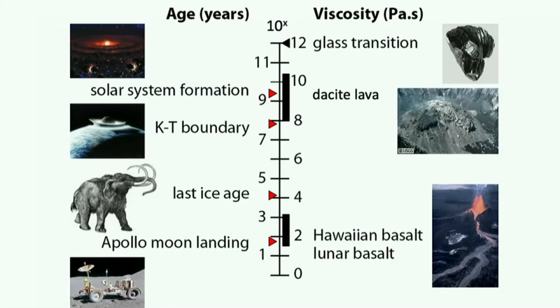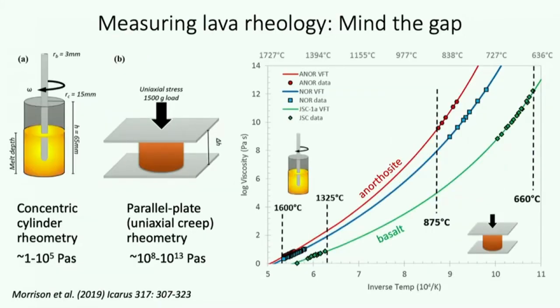All right, another thing that the observant among you will have picked up on is that there is a gap in the data. And the reason for that is here we're above the liquidus, right? We can stir this liquid all day long, nothing really should happen to it. Here we're above the glass transition, at such a low temperature that the kinetics of crystallization are really slow, and we can actually keep it as a supercooled liquid. So it is a liquid, it's just not in equilibrium, right? It wants to crystallize, it just can't because the kinetics are too slow. But in the middle range, that's where it would actually crystallize, and we actually do spend a lot of time measuring the rheology of partially crystalline lava, but I'm just not showing it on this diagram because it doesn't fit the rest of the curves, because those are strictly for liquids.